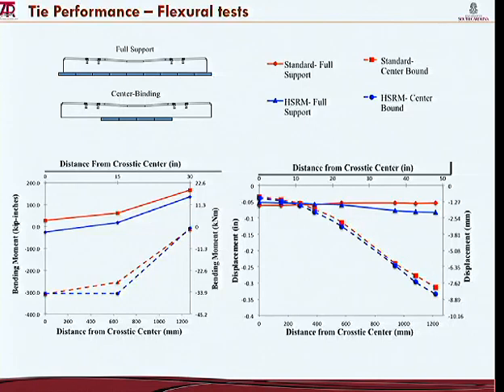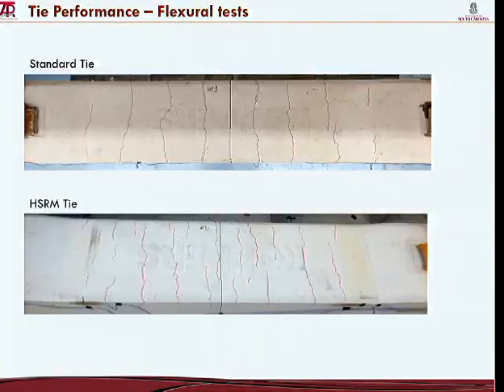But very comparable otherwise. What is important to notice here is the cracking pattern. This is a standard tie where we see full width cracks through the tie, as opposed to the HSRM tie where you do have more cracks, but they are shorter and hopefully more shallow. We didn't have a way of looking at how deep these cracks went. But this is a typical behavior of resilient material or more flexible material as opposed to the full-length cracks that develop.